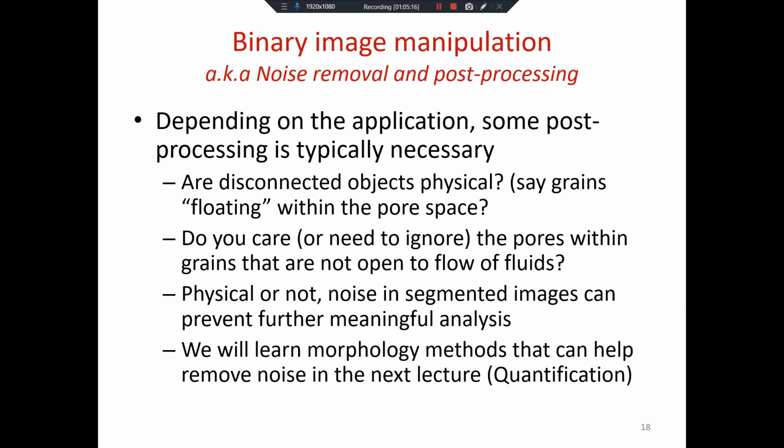Small features make unstable simulations. But if they're small and volumetrically are not a lot of the image, and if you're concerned about the permeability, small features, unless they're really sitting in the middle of the pore space, will not really affect your permeability calculation all that much. Permeability overall is very sensitive to what's in the middle of the pore space, and it's the larger features that dominate.